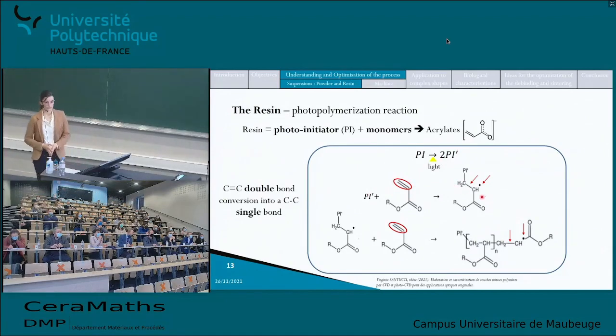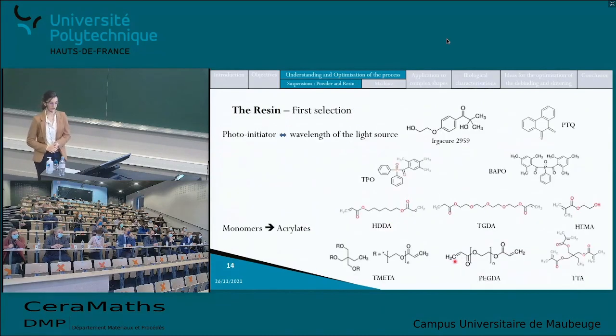So, thanks to a literature study, I did the first selection of the components of the resin. The photoinitiator has to be chosen considering the wavelength of the light source, and I decided to choose 4 different photoinitiators: the Irgacure, the PTQ, the BAPO, and the TPO, in accordance with what I found in the literature and what was used with bioceramic material. And I also selected 6 different acrylates with different functionalities: a diacrylate, a methacrylate, a triacrylate. So these are the 3 functionalities.